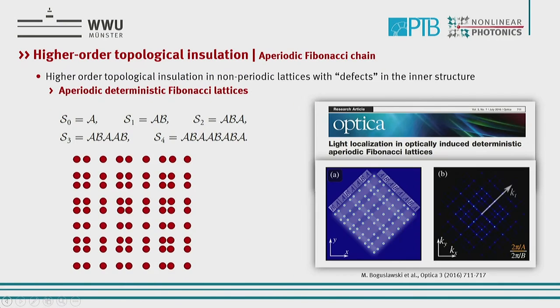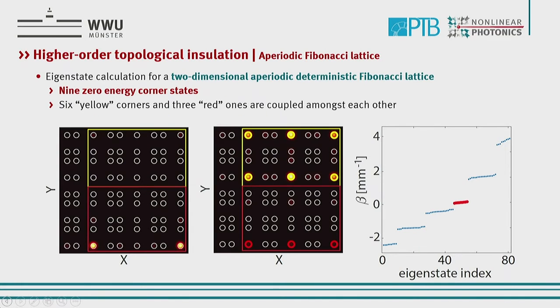And in fact, you can do that because we have structures in photonic lattices that are in a way aperiodic, and this aperiodicity allows you also to get another symmetry breaking. And this symmetry breaking can best be done if you, for example, realize an aperiodic Fibonacci lattice. We have done this in earlier times and practiced it. So now we look at this Fibonacci lattice and how light propagates in it. What we want to see is such a Chern number phase transition.